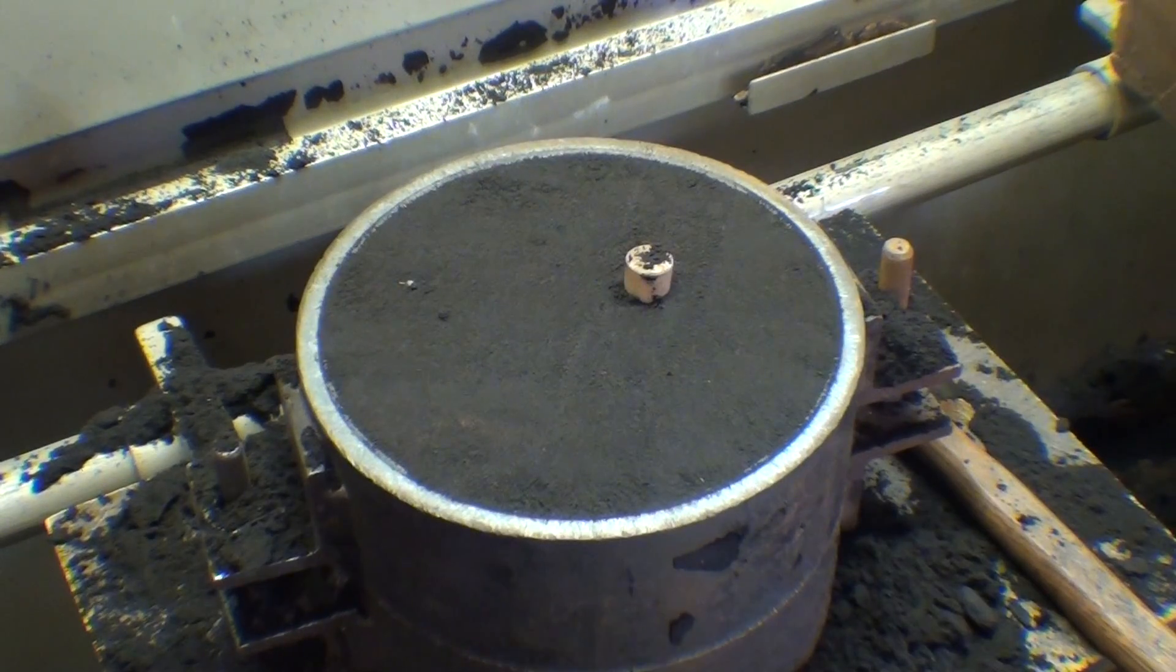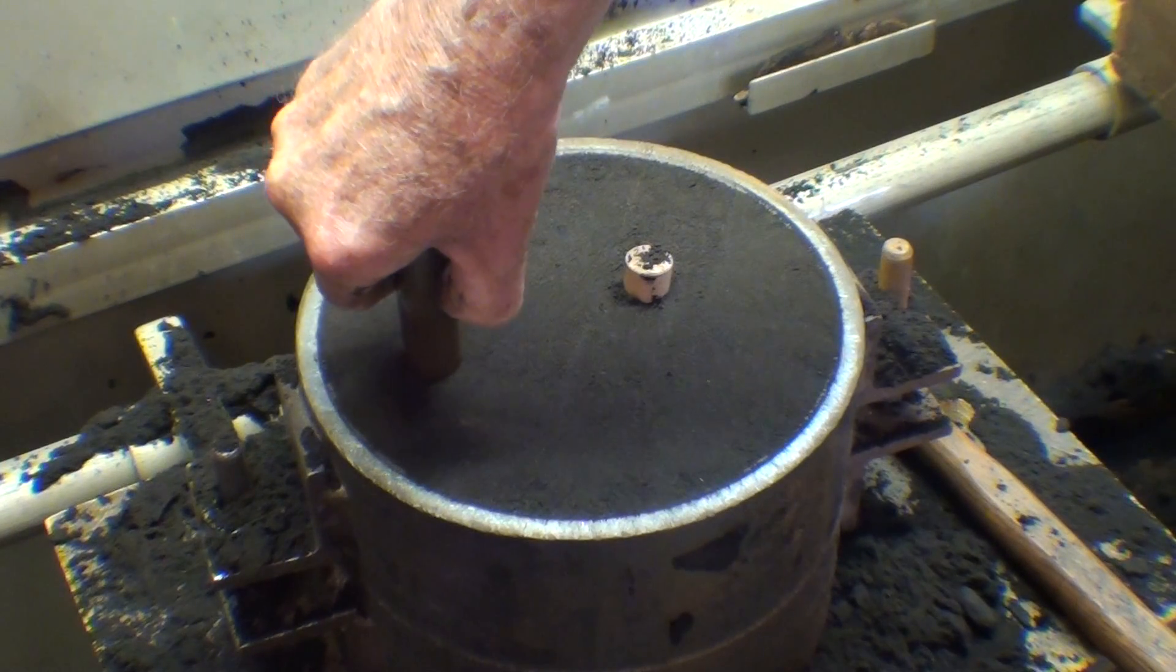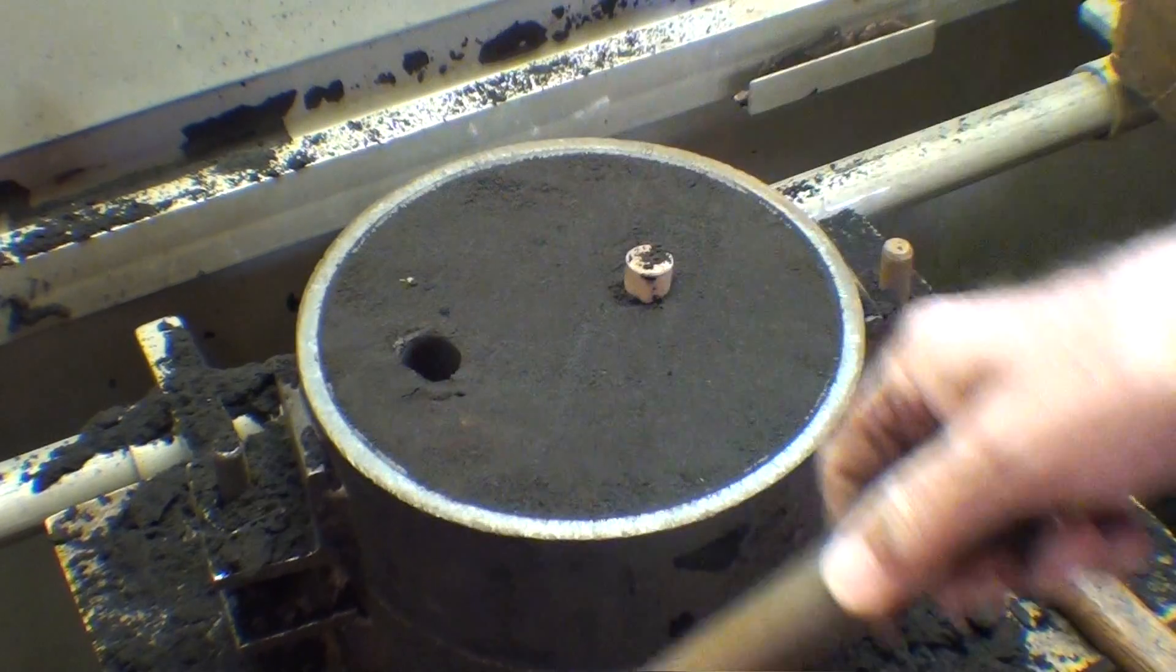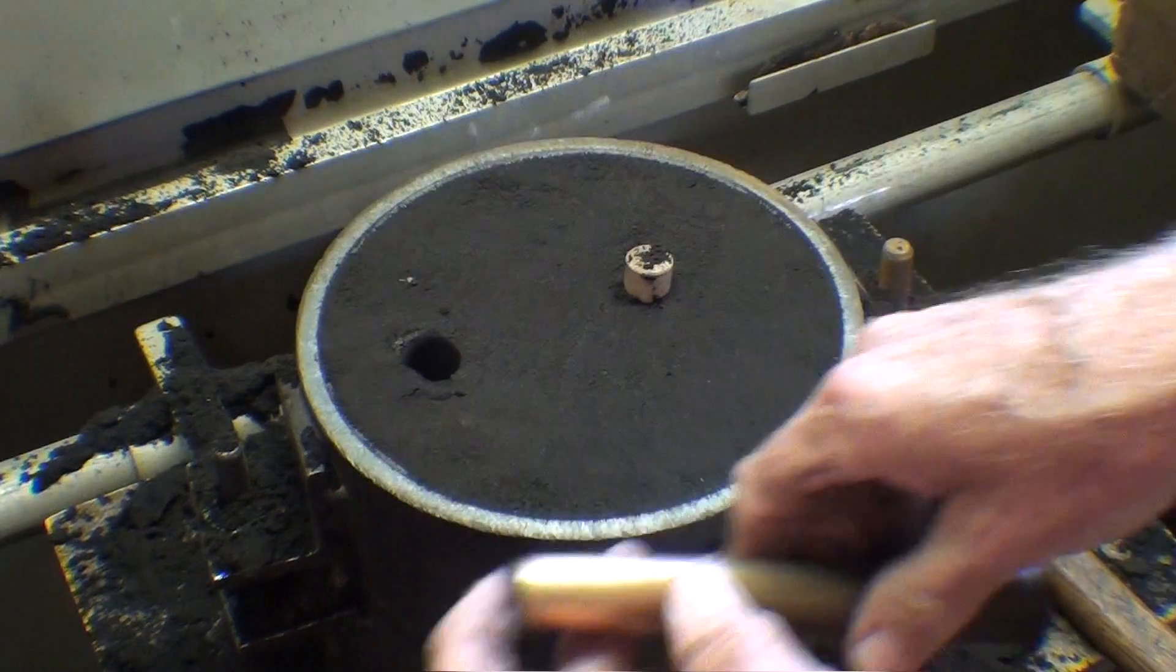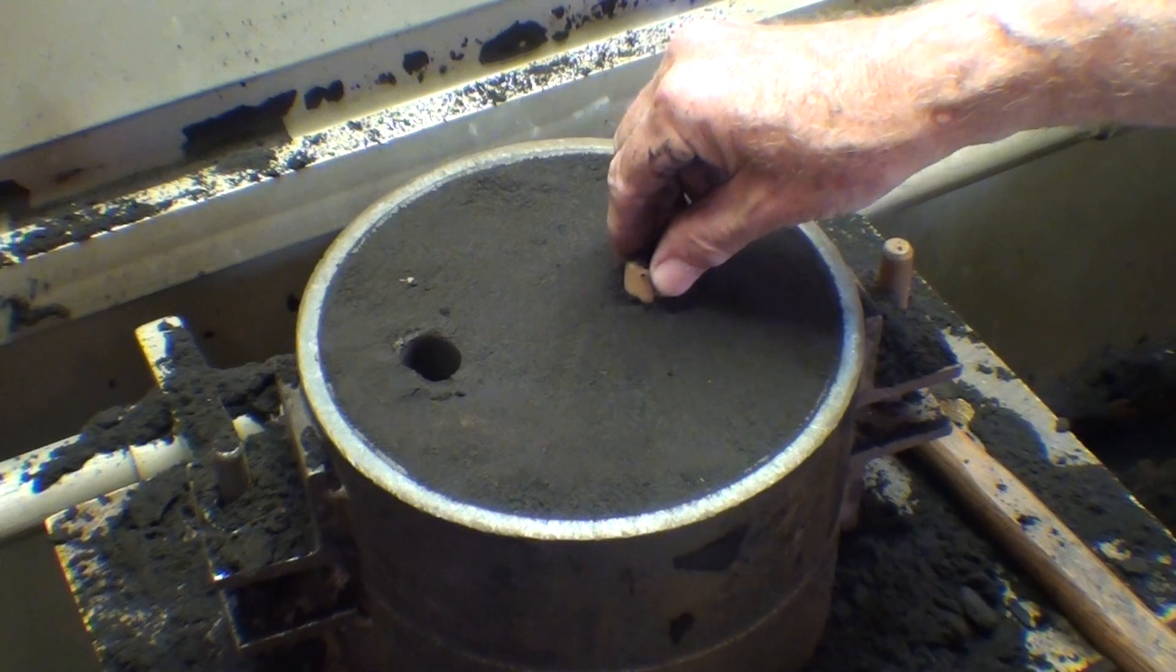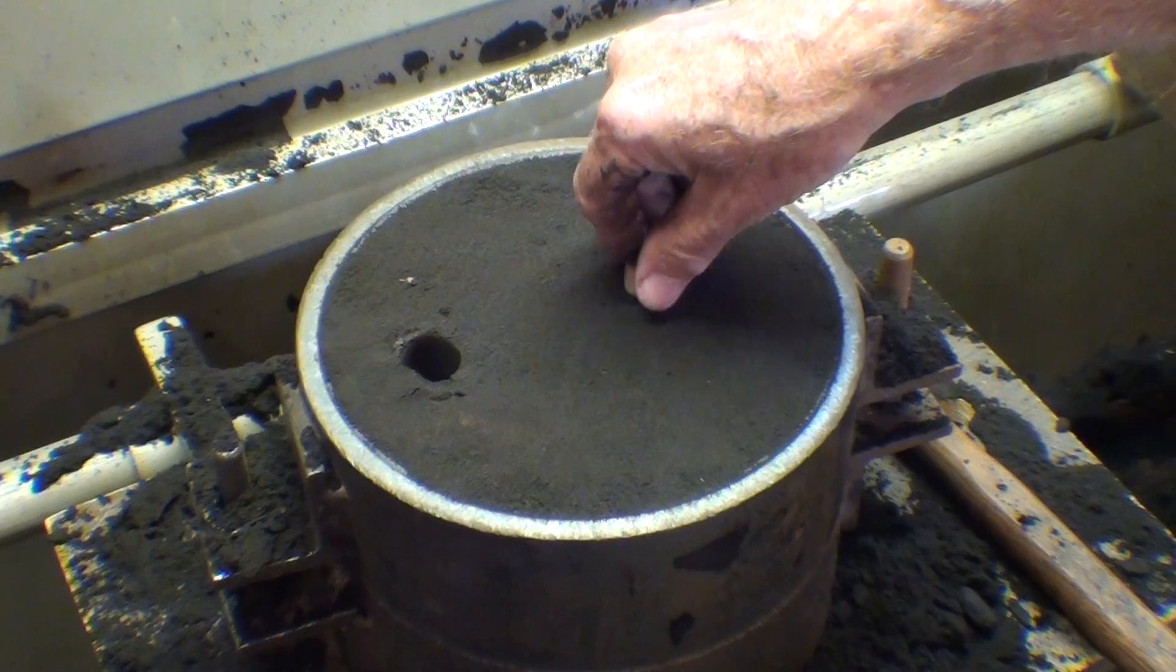It's all rammed up. I'm going to cut a sprue hole right there, being careful not to strike the pattern. I use my thumb as a depth gauge. And I'll remove this riser. Remember it's tapered, so it'll pull right out, I'm quite confident.